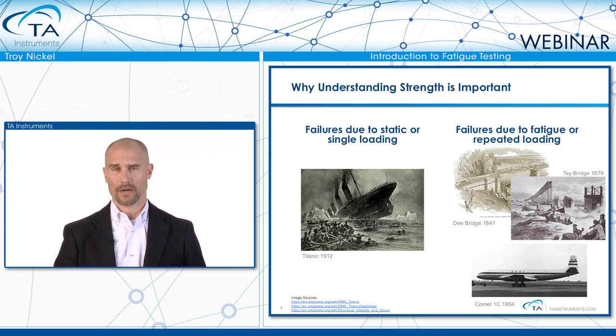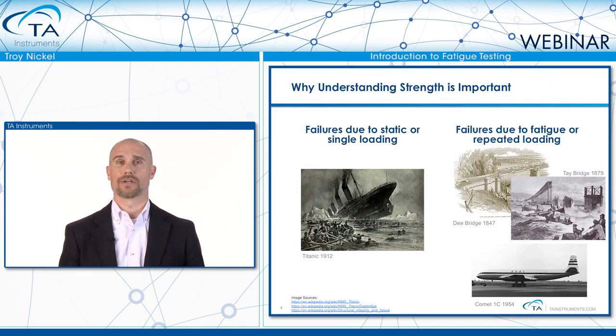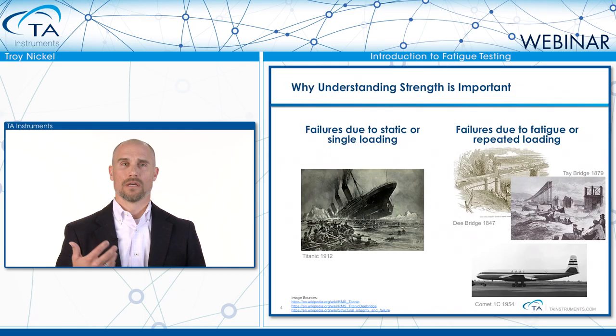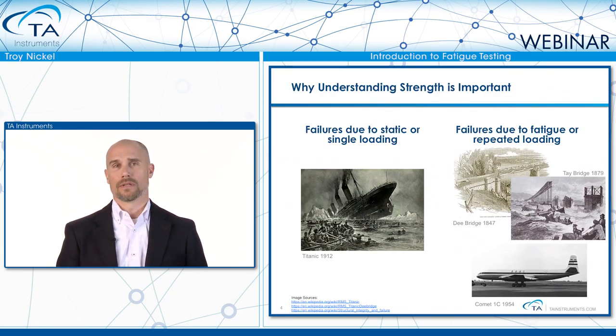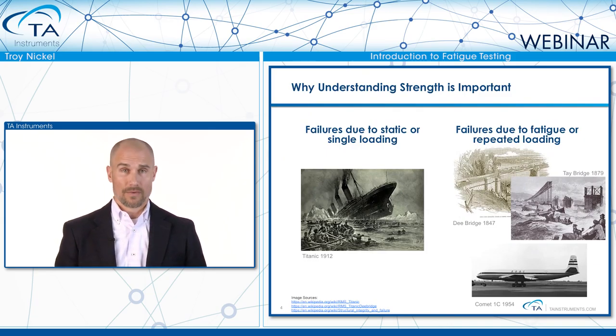Another example is in the airline industry — the Comet 1C. Two airlines crashed due to decompression. There was a stress concentration around the windows, and the failure to appreciate how cracks initiate and propagate in structures like this led to failure. These events challenge all of us to understand how we can evaluate materials better and design structures with better understanding.